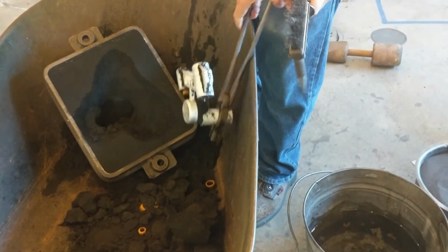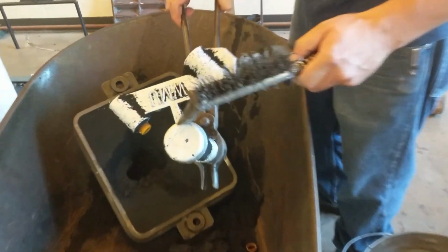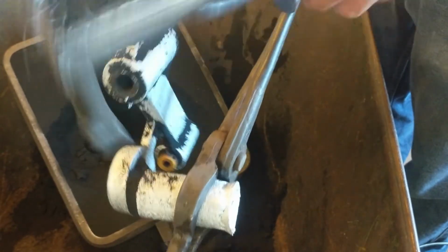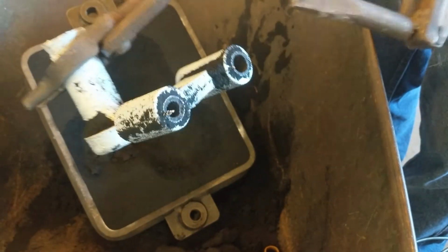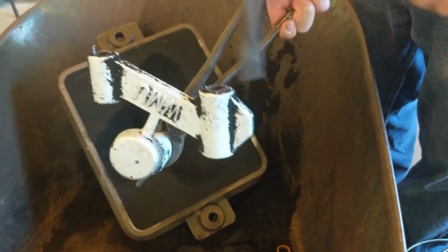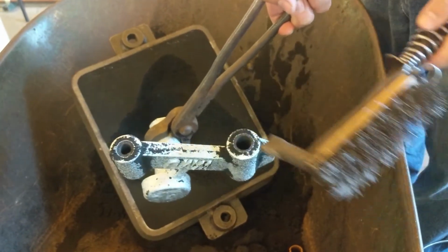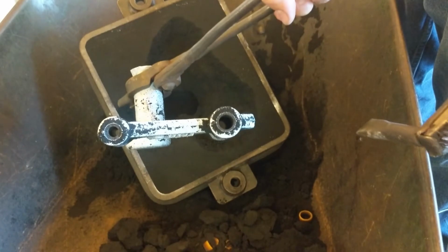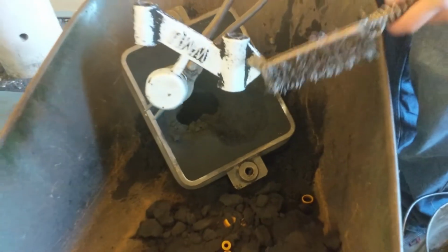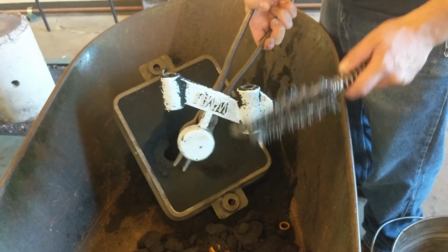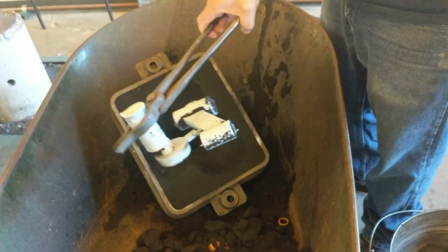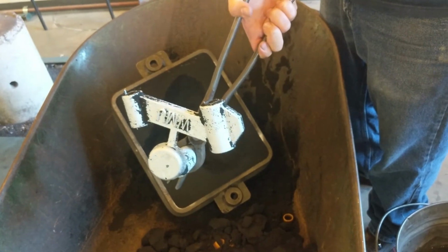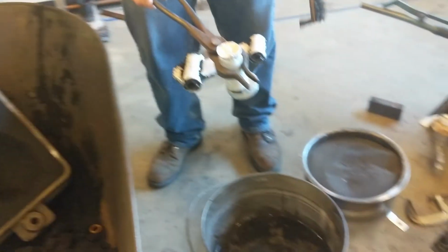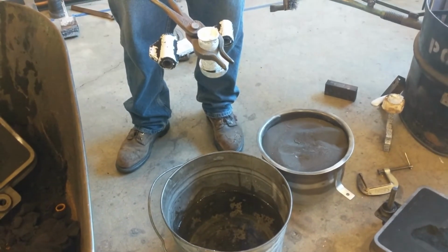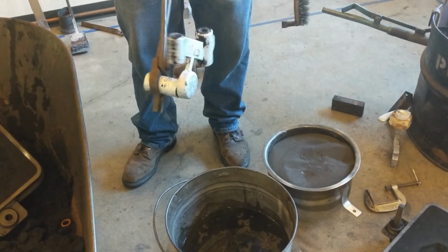And now that it's out, before I quench it, you can see the completed gate and runner system. You can see where the pouring sprue was attached. And once this has been cooled, I'll clean our core material out. But here you can see that the cores made through holes in the sides of the part. And that's the purpose of those cores, is to generate the type of geometry that you can't make with a traditional cope and drag style mold. So I'll get these cooled off, and then we'll move on to sectioning these, and we'll take a look at the finished castings.